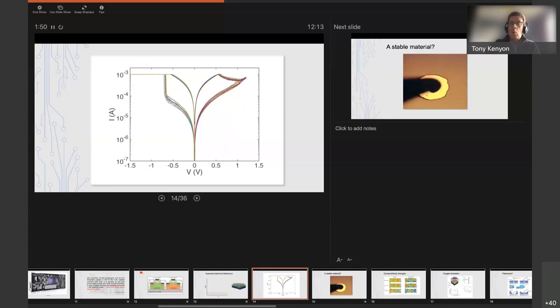The problem is, although you get very nice switching behavior, there are some issues with stability. You really don't want to have metals that are diffusing in CMOS electronics. So a fab really doesn't like that. So although the switching characteristics might be quite nice, a fab won't want to work with those materials. Similarly, with polymer materials, they could be useful for plastic electronics, but in mainstream CMOS, they won't be integrated because their temperature stability is too poor.